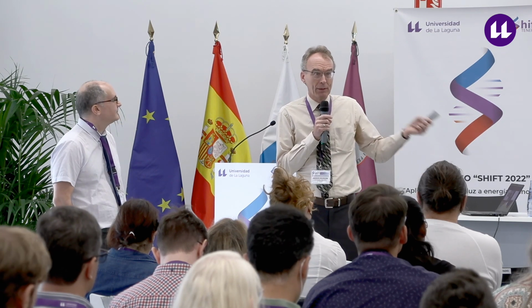Yeah, but I mean, beyond our popular but Laporte-forbidden limited lanthanides, in any sensor it will be relevant to have, talking roughly, an average of 20 points better than one of 10 points. So that will be extrapolable to any different thermometer, right? Like the importance of reporting, taking into account the brightness. The brightness of a probe is always important, whether it's a Boltzmann thermometer or energy transfer. The noise, which is determined by the intensity of your signal, determines the preciseness with which you can determine temperature.